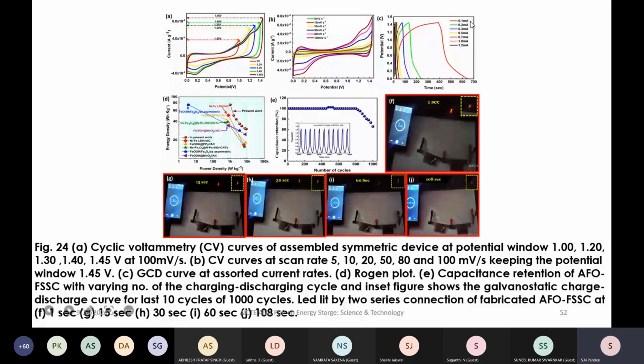Then in the D part, one can see the Ragone plot. In the Ragone plot, one can see that the present work is here. The energy density is very high, and the power density and energy density relation is given here. Coming to this E part, that is capacitance retention, which is very important. One can see that after 1000 cycles, up to about 800 cycles the retention is very good. After that it is decreasing, but only up to about 70%.